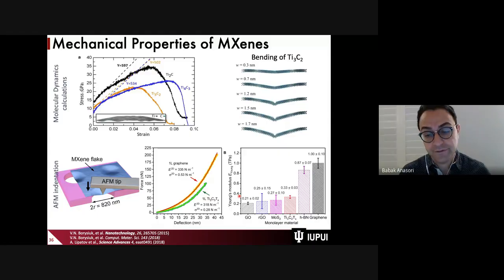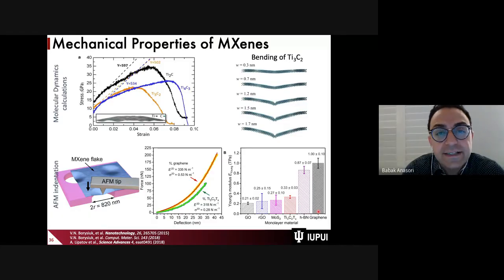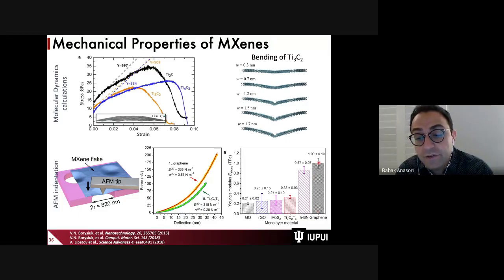Now, one unique feature is that if you're looking at graphene and hexagonal boron nitride, these are the values that we can get only if we grow a single layer, which from a mechanical engineering perspective doesn't really help us, because we do not need just a single layer. We need a lot of material to put in the composite. So it is great to have this very high Young's modulus, but can we put it in our composites? The answer is no, because we only have a single layer. And also this is not even hydrophilic, so it has a very hard time bonding to other material. Now for MXenes, this is the one that we can make in large quantity.